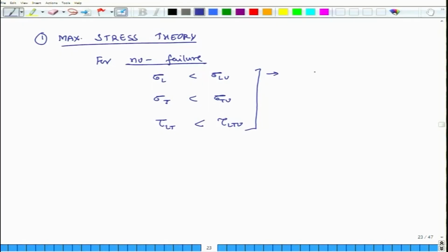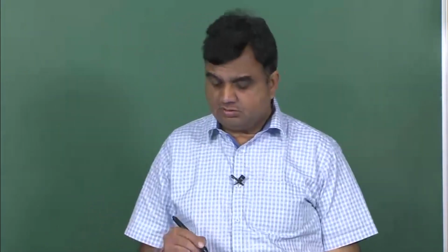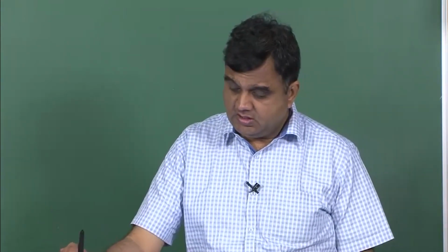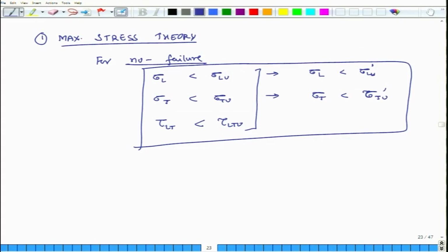Now, there could be a case that sigma L is negative. Then the condition would be that the magnitude of sigma L should be less than sigma Lu prime. And if sigma T is negative, then it should be compared with sigma Tu prime. So if the stress is compressive, you have to compare it with its compressive strength in the appropriate direction. So these 5 conditions are there, and as long as all of them are true, there is no failure; even if one condition gets violated, the material is going to fail. This is the first theory for failure of composite materials.